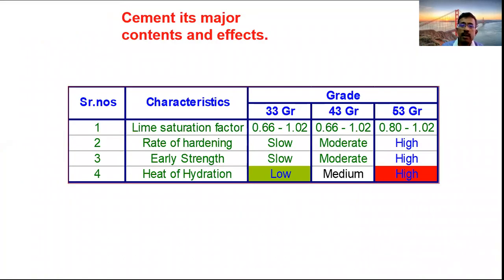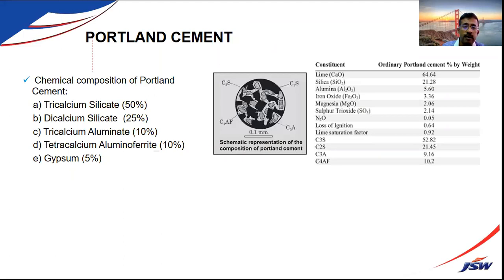So, what are the constituents of cement? The various grades of cement. I'm showing the lime saturation factor. What is the lime saturation? Then the heat of hydration. I'm showing here early strength and rate of hardening. As you go from 33 grade to 53 grade cement, all the parameters will keep changing. And the main active ingredients in the cement are tricalcium silicate, dicalcium silicate, tricalcium aluminate, and tetracalcium aluminoferrate, along with gypsum. So in any cement, generally, you have these factors.